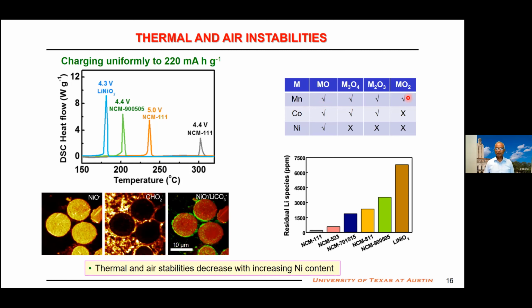You can have manganese 3+ or manganese 4+, stable in air. Cobalt, you can have up to Co2O3. We do not have CoO2. Nickel, you have only NiO, that's it. Not even a 3+ oxide. And that's why nickel 3+ reacts very rapidly with air.